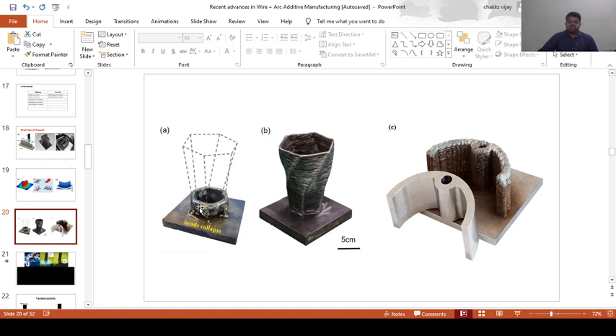Once all the process parameters are well optimized, we get a very fine component with very high geometrical fidelity like this. Once we have fabricated this component, it is machined very smoothly to attain a glossy surface. On seeing the surface, we cannot blindly conclude that wire additive manufacturing doesn't work. We should not jump to that conclusion. After machining, this component will look just like a brand new one.